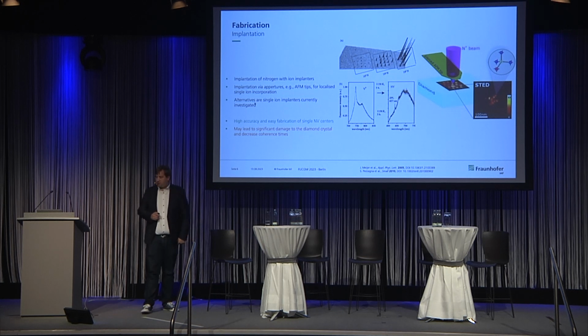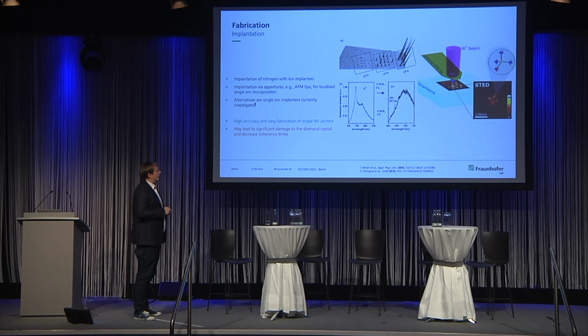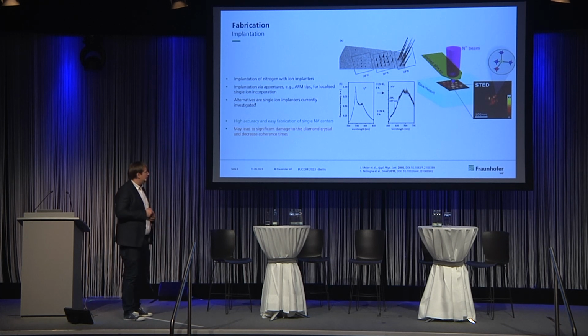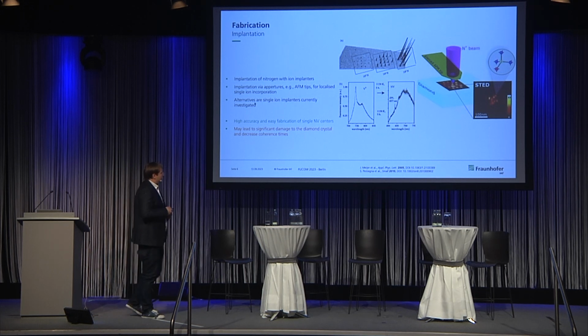How can we integrate these NV centers into diamond? There is a straightforward approach that is still used to quite an extent. We just use a nitrogen gas source and implant the ions into the diamond. If you're working with materials, you will know that implanting ions into materials will lead to some damage to the structure.